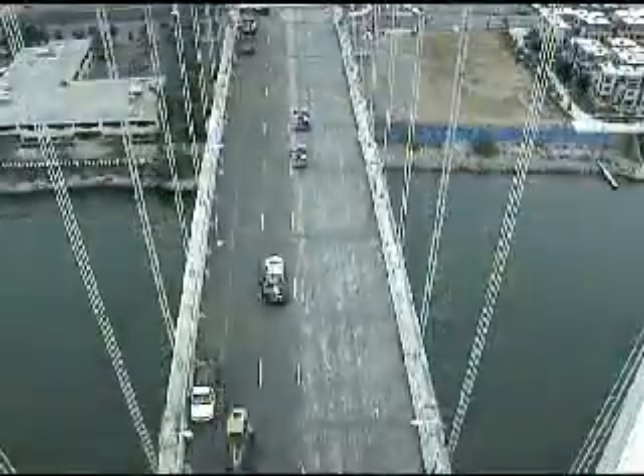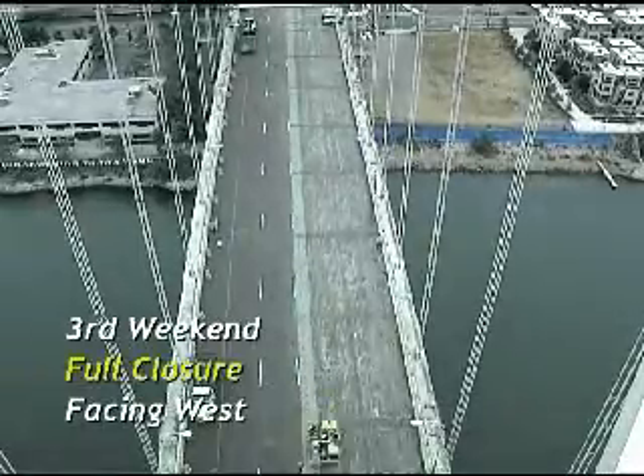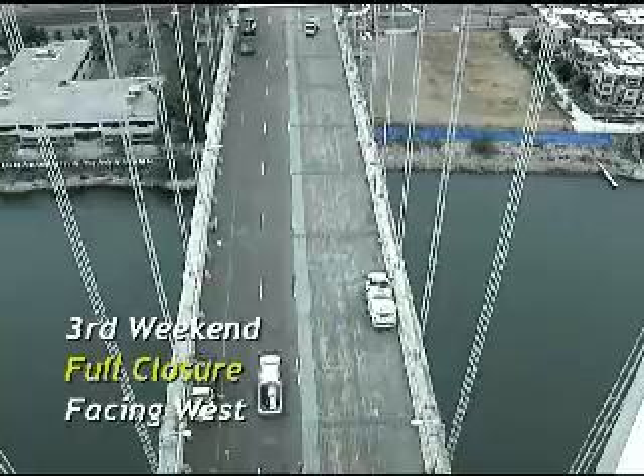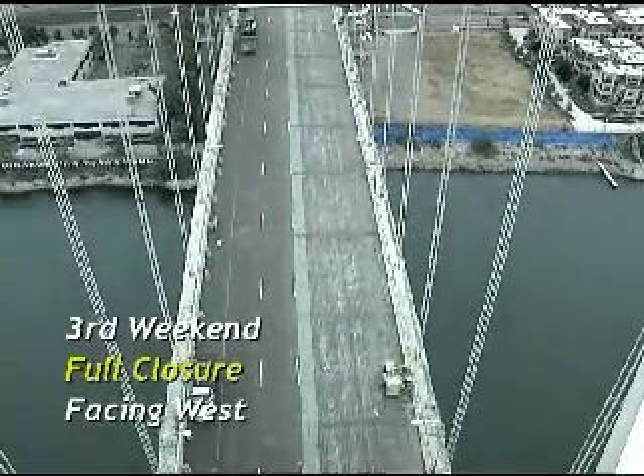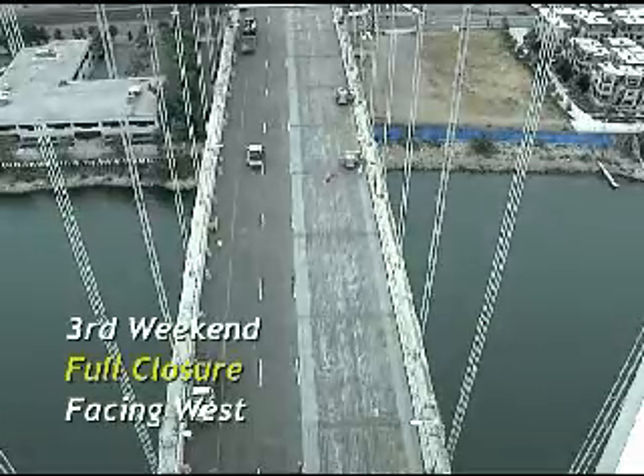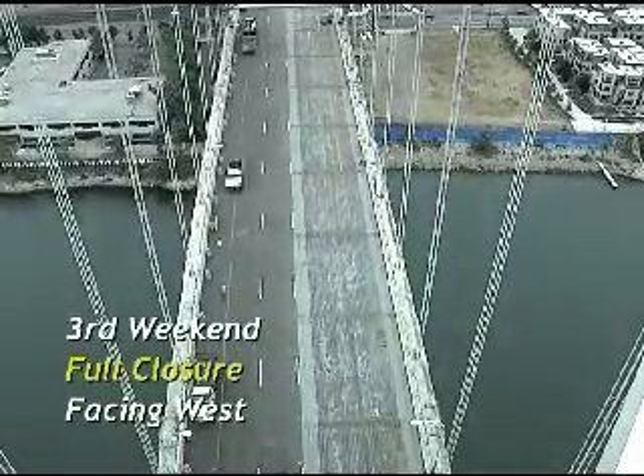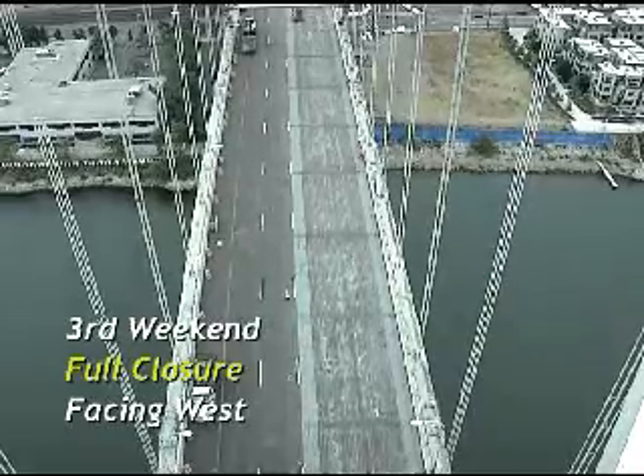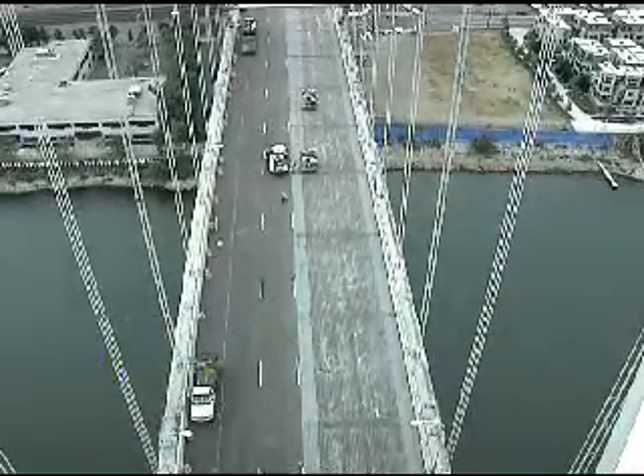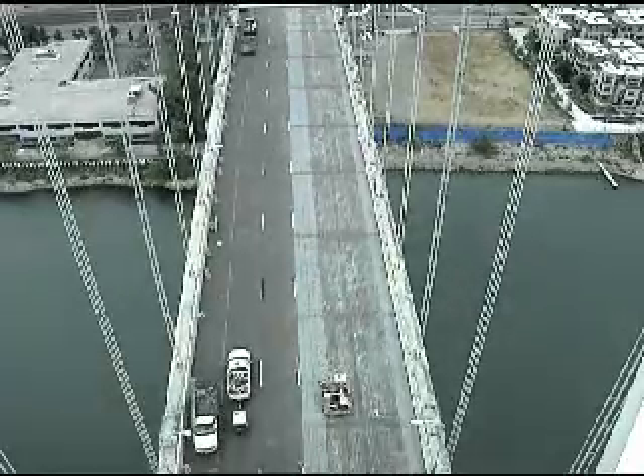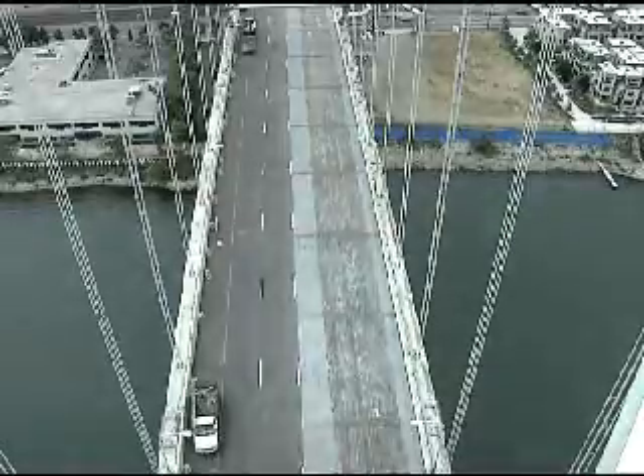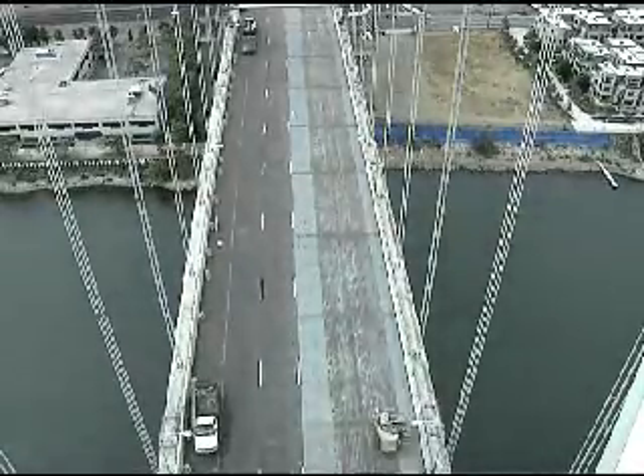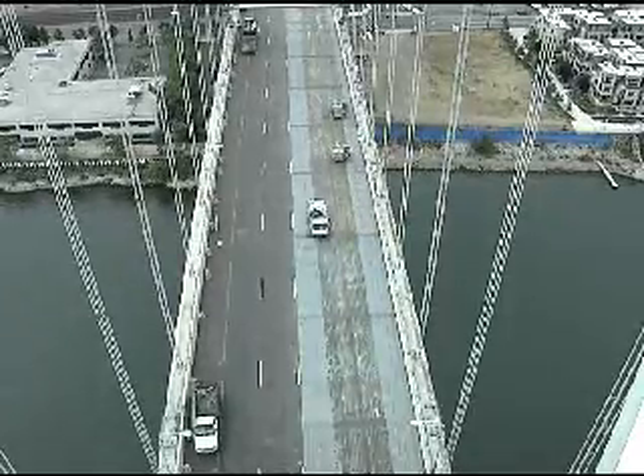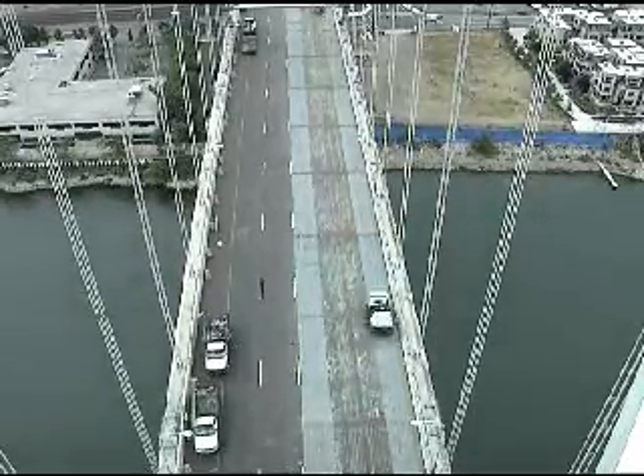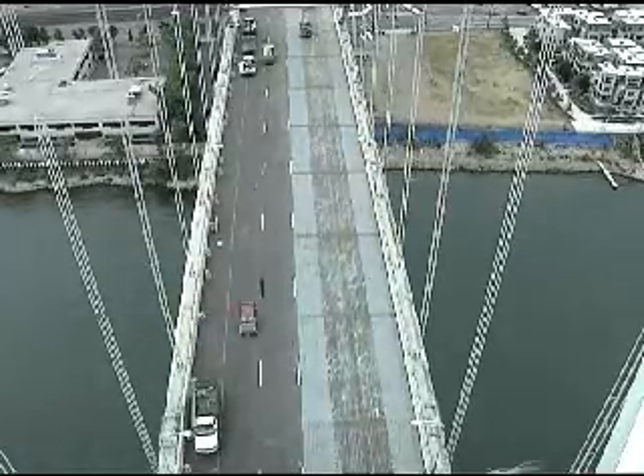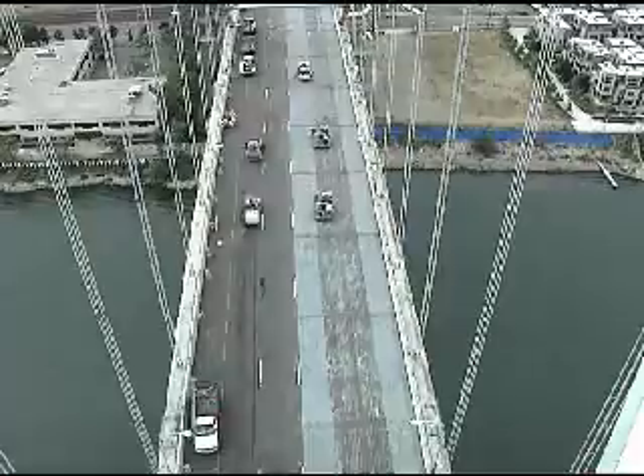So after the contractor removed all the existing asphalt and chipped around all the bolts and got everything as clean as possible, we had to do a final operation to clean the deck and also to provide a nice textured surface for the new asphalt to stick to. So that was done by a process of shot blasting the steel deck with 2 mobile shot blasters. The 2 mobile shot blasters have blasting heads about 30 inches wide, and they can travel along at varying speed and shoot very small, tiny steel shot at a very high speed at the steel deck to remove any latents or residual oil or film or anything that's left on the steel deck, and also provides a little bit of surface texture onto that steel for the spray bond coat and the asphalt to adhere to.